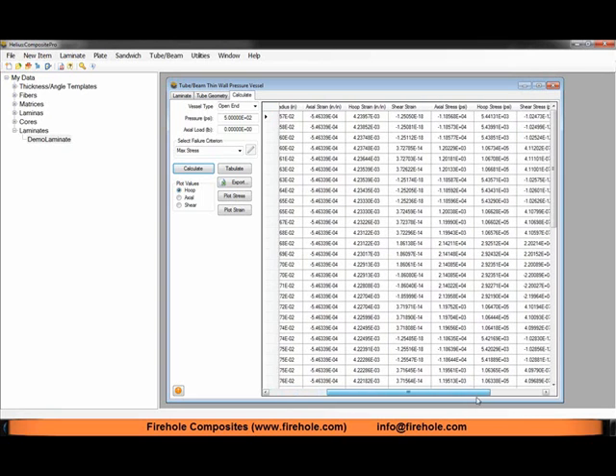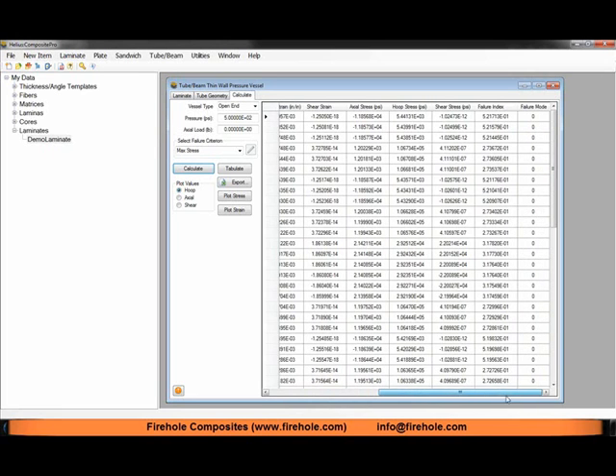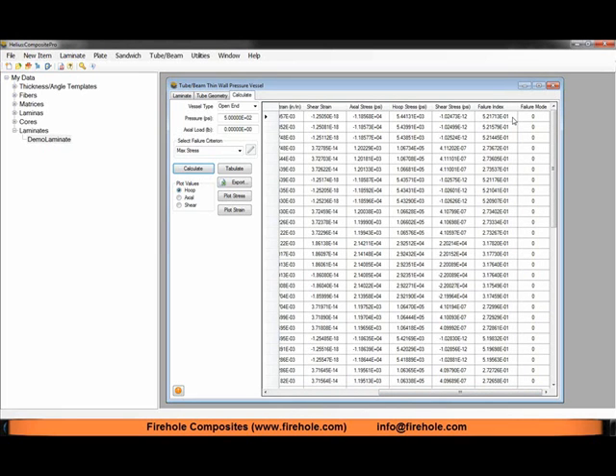Moving along we have the strain in the axial hoop and shear directions for each of our composite points, and also the axial hoop and shear stresses for all of our points. Finally, we have the failure index and failure mode for each of our composite layers. We have a failure index of 0.52, so we're roughly 52% of the way to failure in this individual composite ply. Some quick calculation says we might be able to bump up this internal pressure to 1,000 before we start seeing some failure. We'll go ahead and do that and see what happens.